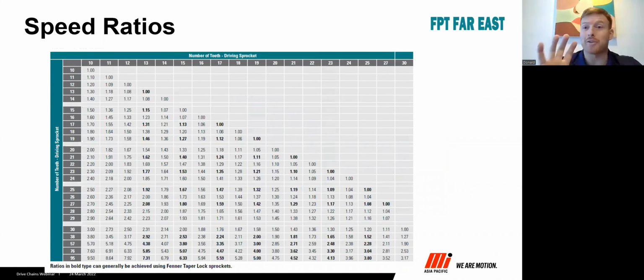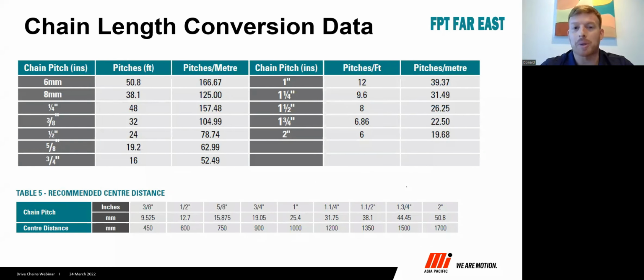We also then have the ratio, which is the change of speed between the two shafts. This is just a quick guideline on the sprocket. So if you have, for example, a 19 tooth and a 19 tooth, your ratio is 1. Pretty straightforward. If you have a 30 tooth and a 19 tooth, your ratio is 1.58. That'll be the speed ratio change. This is in our catalog for reference and ease of use. We then also need to change the pitch of the chain into the length of the chain. I won't get into too much of that now.